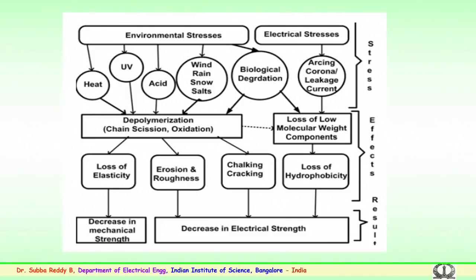As mentioned, we have arcing on the surface because of the formation of dry or wet bands. Over a period of time, or during monsoon conditions or early morning conditions, fog or mist on the insulator surface, snow and mist, along with the pollutants and contaminants, start conducting on the surface because of the non-uniformity of the coating or the pollutants collected, and also due to wind conditions. The surface becomes conducting in some portions and not in others. So dry band or wet band formations happen on the surface, and small arcings or partial arcs happen.